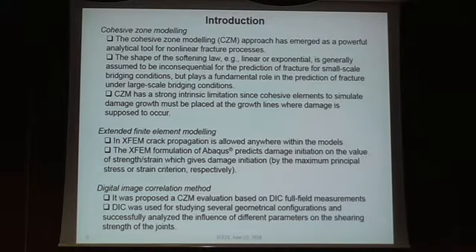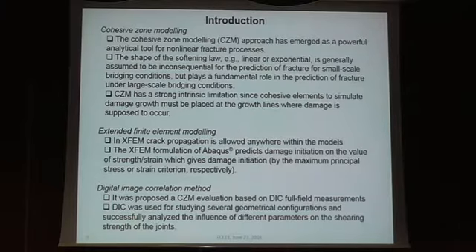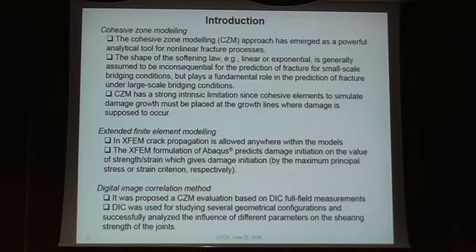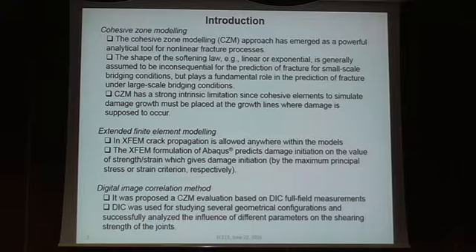On the other hand, extended finite element modeling is used nowadays more and more. You can have crack propagation anywhere in the model you consider. We have used Abaqus for modeling, which means that damage initiation strength or strain criteria of maximum value have been used. Experimentally, there were many studies which used DIC for studying what happens in the adhesive layer, looking at the influence of different parameters.